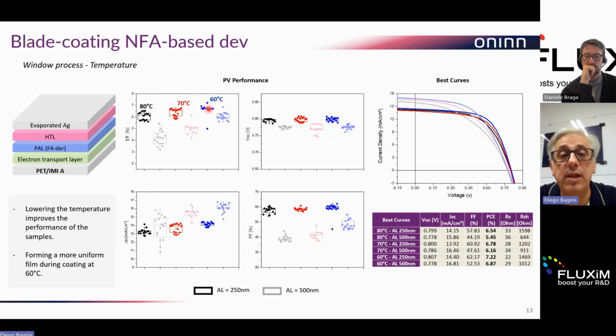And over this, if we compare two different photoactive layer thicknesses, 250 nanometer and 500 nanometer, you see that the gap between the results is also reduced when comparing the temperature. What does this mean? That we have much more tolerance to variation during the coating in the web, and so it means higher yield. We have a slide dedicated to that later.